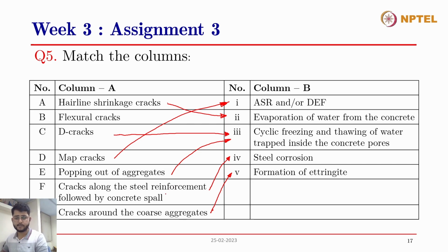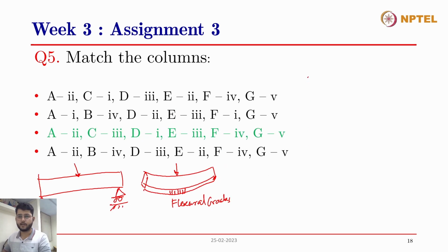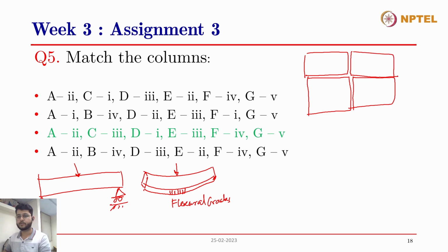The D cracks, again, have been well discussed in the lecture as well. This is due to the cyclic freezing and thawing of water trapped inside the concrete pores. This is the third option. So what essentially happens is, when slabs are cast there are joints between the slabs, and these joints are saturation points. Whenever these slabs are exposed to water or humidity, these joints are generally filled with water. Due to the availability of this water, it can get inside the concrete elements, and due to the freezing process it will cause these cracks, and the cracks will appear in the shape of D, away from the saturation points, and this is how it appears.